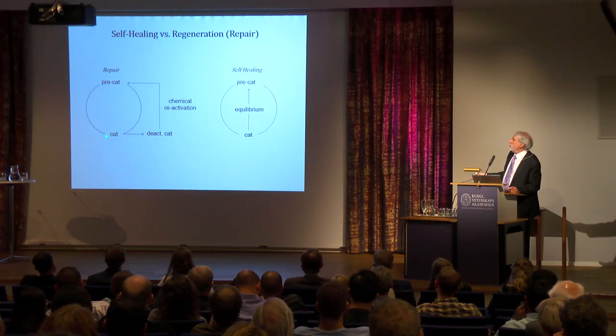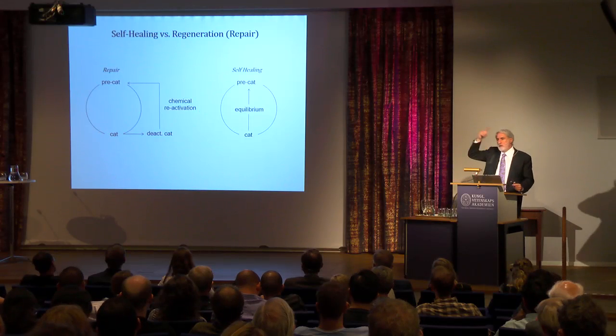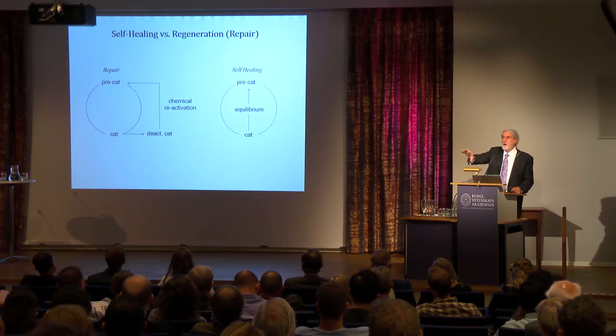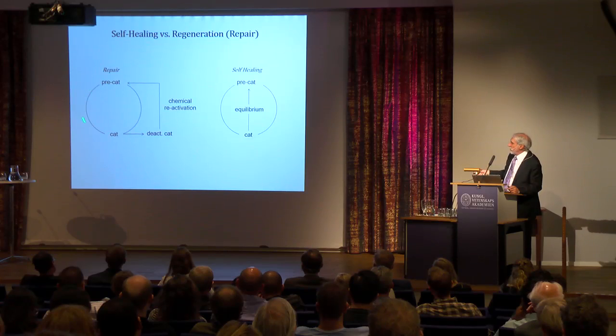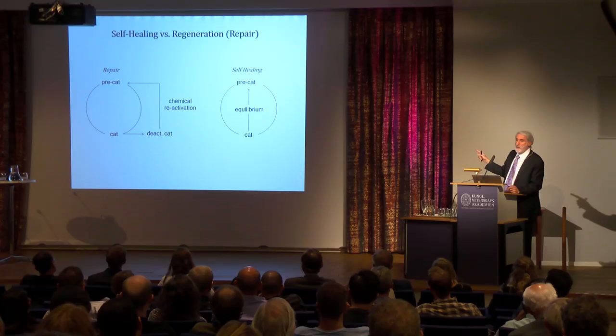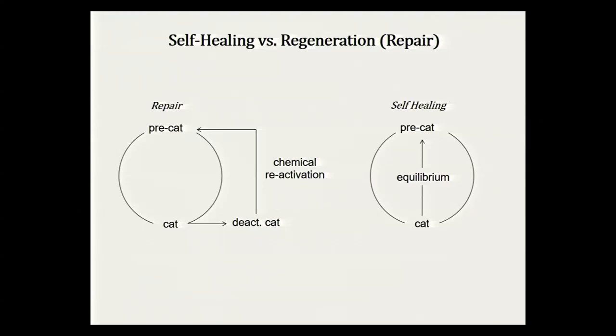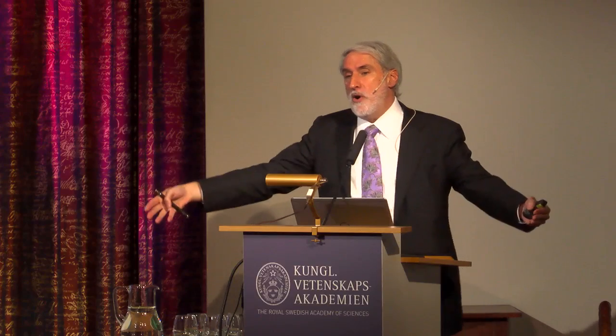Now, in chemistry, we don't make self-healing catalysts. What we do is we run a catalyst for a period of time, and then it dies. And then what we do is we regenerate it. All right? And that's how our catalysis is performed. Believe it or not, this is the first catalyst that's self-healing. This cobalt catalyst never dies. We set up the chemistry that as it's operating, it's always doing the self-assembly process. So if some of it starts to fall apart, as it's operating, it actually can re-self-assemble itself as it's doing water oxidation.